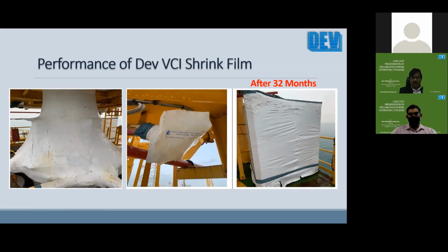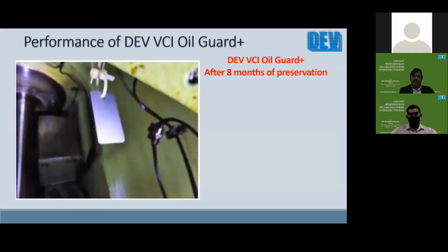Similarly, you can see after 8 months of the preservation of an engine area using the oil guard, there is no speck of rust or corrosion in the entire parts inside, because this corrosion monitoring coupon is a carbon steel piece which is representative. So if there is going to be moisture, this is going to corrode first before the other forged or machined parts start to corrode. That way we try to keep it as a test and to prove that the entire system is remaining preserved internally.